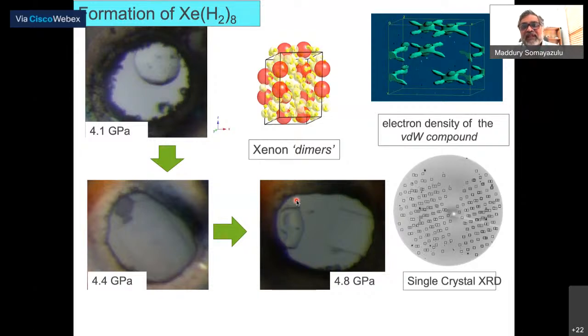So that was when we started looking at xenon and hydrogen. And this was, again, full of surprises to us. First of all, we found that you can form a huge number of phases. And I'll just try to lead you through these pictographs here. This is what you would see when looking through a diamond anvil cell if you take a mixture of xenon and hydrogen, which would be just a homogeneous mixture because it's completely miscible.